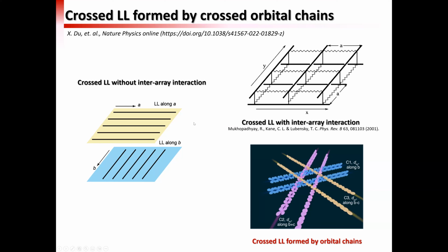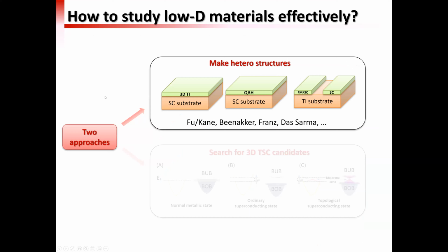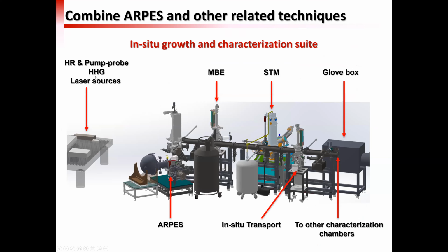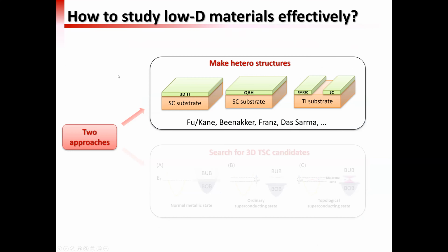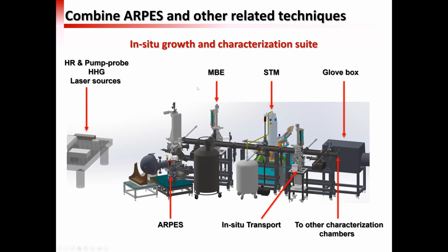In the last part, I will skip that; if anyone is interested, you can ask. Because I learned that in RISE you're trying to make a vacuum interconnected system, that's what we have been doing. To study low dimensional materials, a lot of them are environment sensitive, so we need to keep them in ultra high vacuum. We made a suite of characterization tools, using ARPES and other related techniques, connected by vacuum highways, so you can grow the sample and then measure it with STM, ARPES or even transport.